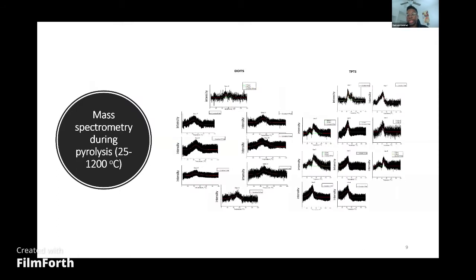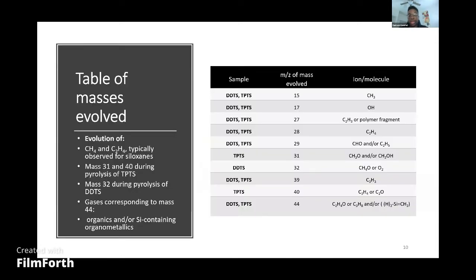Because we coupled the TG-DSC to a mass spectrometer, we were also able to observe the evolution of gases during the pyrolysis of these materials as shown by these peaks, and the results are summarized in this table. As expected, which is usual during the pyrolysis of siloxanes, we do see the evolution of organics such as CH4 as well as C2H4. During the pyrolysis of TPTS, we observed the evolution of gases corresponding to mass 31 and mass 40. In contrast, during the pyrolysis of the DDTS, which is not observed during the pyrolysis of TPTS, is the evolution of gases corresponding to mass 32.